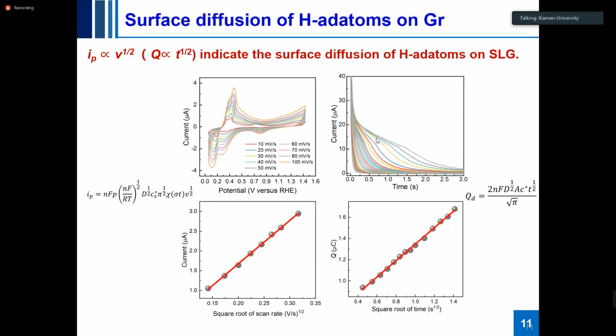We also performed the experiment when the surface was activated completely. We can perform the experiment with cyclic voltammetry or also potential step. For the cyclic voltammetry, we find that the stripping peak current is in proportion to the square root of the scanning rate. And for the potential step in the transient state, we can see that the integral charge is in proportion to the square root of time. So this is typically a diffusion process in electrochemistry.